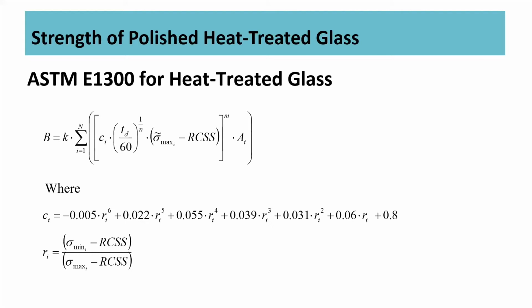So when we use the analytical procedure of ASTM E1300, and I don't want to dig too deeply into these long equations, but what it allows us to do is to account for the geometry, that's including the long and short dimensions. We can actually incorporate different edge conditions or edge support conditions, and also account for the duration of the load. That's what this TD is there for. And we can also include the RCSS.